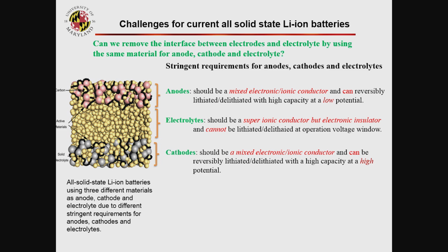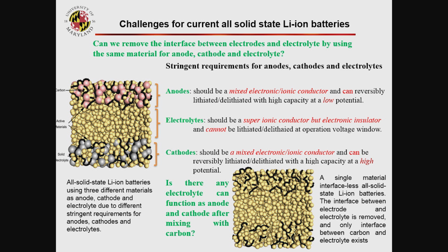How can you make these three different requirements into one material, making it function as three? It's a real challenge. But we want to see if it's possible, and if so, we can really make this kind of battery. So a single electrolyte, anode, electrolyte, we put in a little bit of carbon. We remove the active material. If this material can function as active material, then we can make a single material battery. We remove the electrolyte interface, but we still need a little bit of carbon. So the key question is: is there any electrolyte that, when we mix it with carbon, can become an anode and also a cathode, meaning it has two lithiation-delithiation potentials? Then we check.